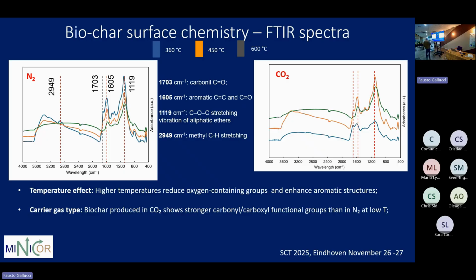And here are some infrared spectra. And we see that there are some characteristic bands, the carbonyl band here, and the aromatic band here. And this ether band, they behave differently if you use different carrier gas, for instance, carbon dioxide, which is interesting for our case, and nitrogen in another case. This measurement was performed by the group in Naples. And we see that with temperature, the higher temperature reduces oxygen-containing groups and enhances aromatic structures. And the carrier gas type, CO2, shows stronger carboxyl functional groups than N2 at low temperature. So they behave differently between nitrogen and carbon dioxide.